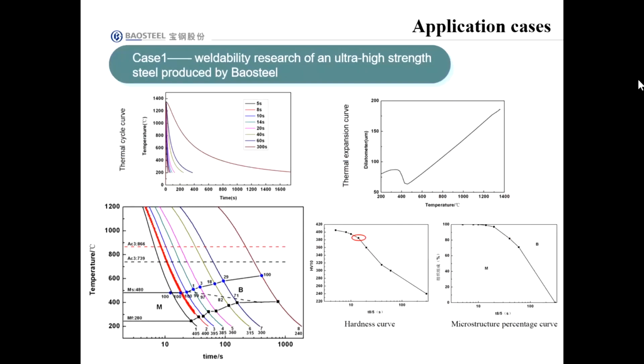This is the final SHCCT diagram of an ultra-high strength steel, including the hardness, microstructure, and transformation information. It can be seen from this SHCCT curve that martensite will be found in a wide range of cooling rates, which means that the steel has a strong tendency of cold cracking. So cold cracking should be paid more attention in establishing their welding process specification.